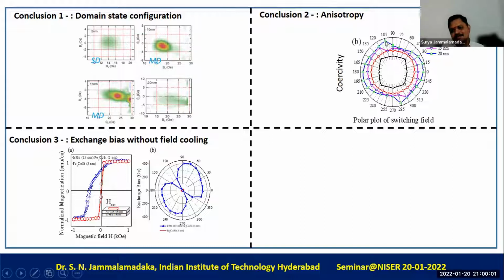But do you think so? Because here, if you look, it is not even isotropic. There is an indication for four-fold anisotropy as well as two-fold. If you look at the bottom corner plot for the exchange bias system, there is definitely two-fold anisotropy, but in the top one I have some observation, but maybe more investigation is needed. We will take your suggestion and try to do FMR. In fact, it was our plan, but because of some reasons, we couldn't do FMR.